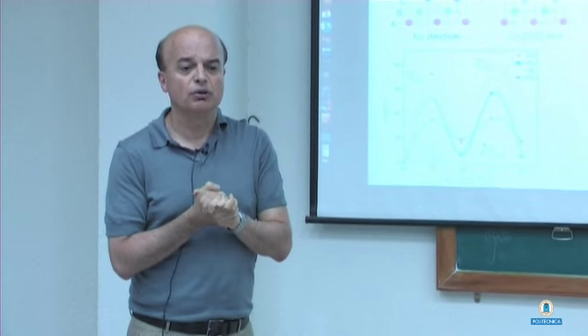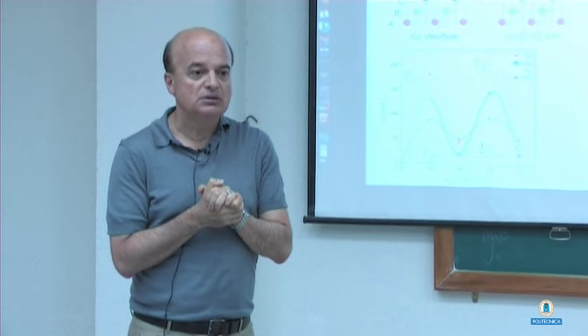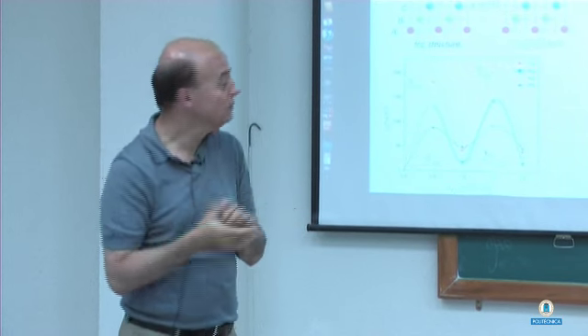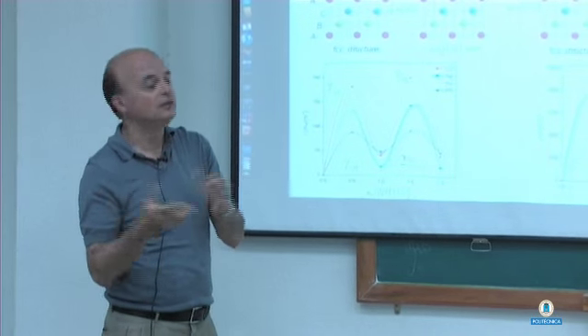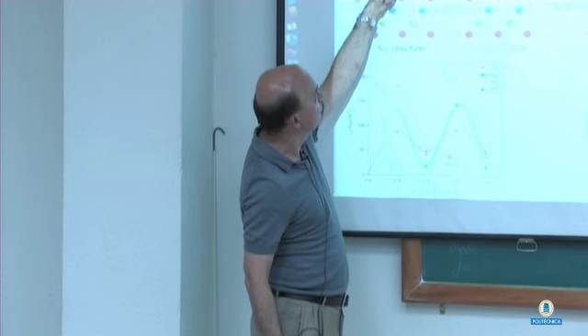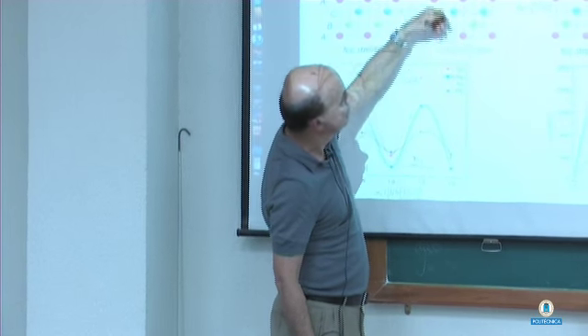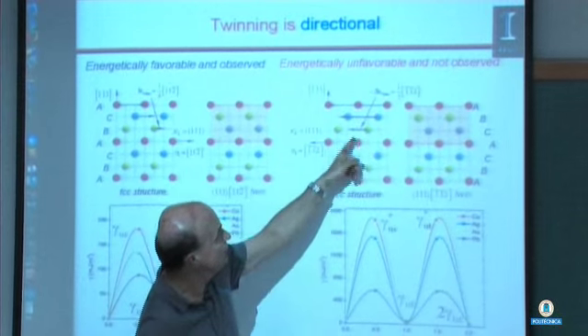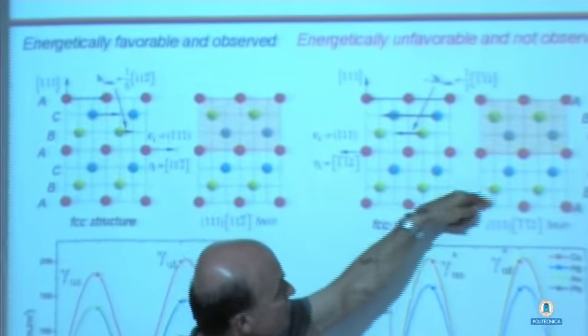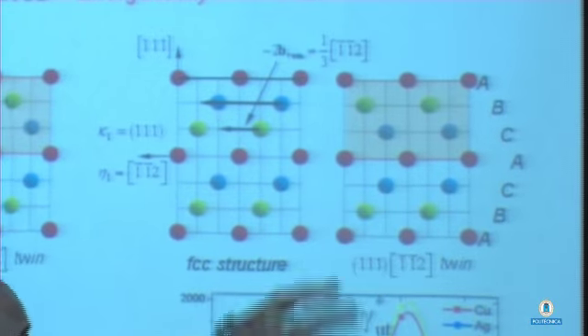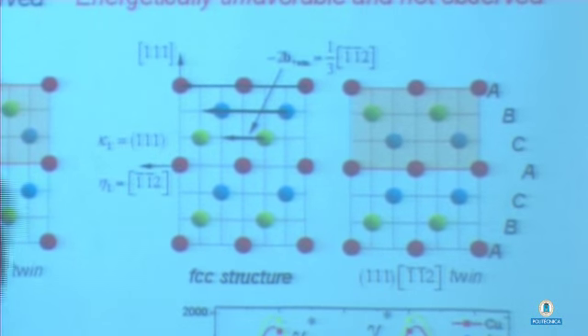There are some other things that can be explained with this model, of course. Twinning is directional. Slip is bidirectional, so you can twin only in one direction. You can't twin in the other direction. This is known, and this model naturally shows you that. So I showed twinning in this direction, right? So this is the twin. That's the mirror plane. Can you twin in the other direction? Well, the final configuration is the same, right?